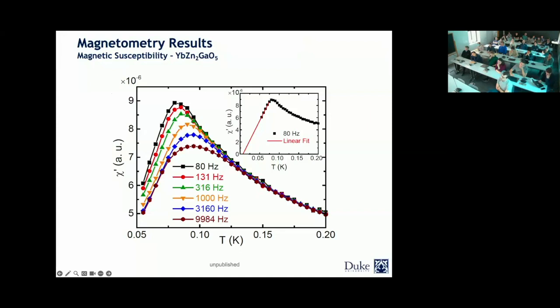And you can see that there is a peak appearing. Here you're looking at the different frequencies, and this is temperature. There's a little bit of a shift, but then it starts to come back. So if you look at the highest frequency and the lowest frequency, the peak is practically at the same temperature.